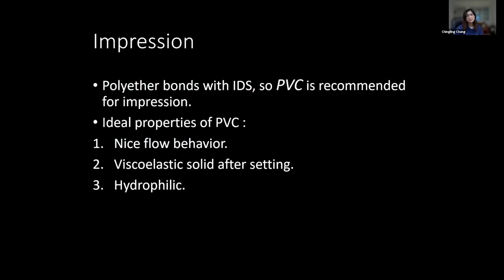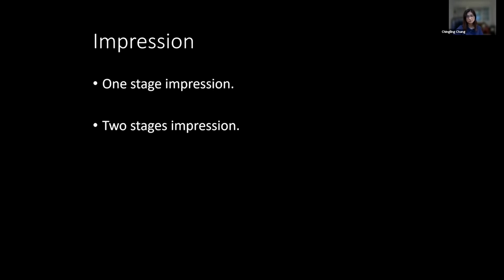Okay, now we're going to talk about impression. Impression is a really critical procedure, and for bonded porcelain restoration, we recommend PVC impression material. The ideal properties for PVC impression material are that they have very nice flow behavior, so we can catch all the detail of our teeth, and they are very viscoelastic and solid after the material is set, and they have hydrophilic properties. So when we work in the mouth, we don't get too much trouble.